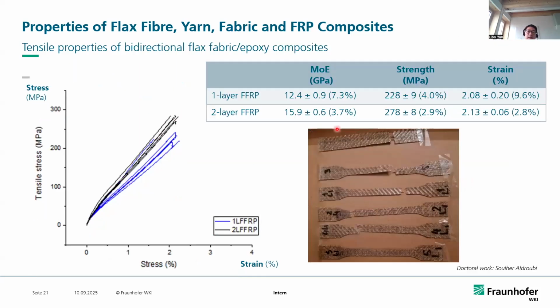In this slide, I would like to give you general information about the tensile properties of flax fabric reinforced polymer composites. As you can see, for the one layer flax fabric reinforced polymer composites, the tensile strength is about 228 megapascal, and the modulus is about 12 gigapascal. If we increase to 2 layers of the flax FRP, we will be able to increase the strength and the stiffness significantly.